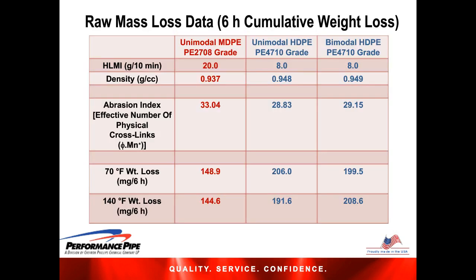This was further validated by simply looking not at the calculated SAR number, but the raw mass loss at the end of the 6 hours of the test. So this is a cumulative weight loss, and that data is shown in the lowest two rows at the 70 degrees and the 140 degrees F temperatures. And you can see quite clearly in the raw data itself that we see a fairly significant difference, with both of the high-density resins showing much higher wear on a relative basis compared to the medium-density resin.